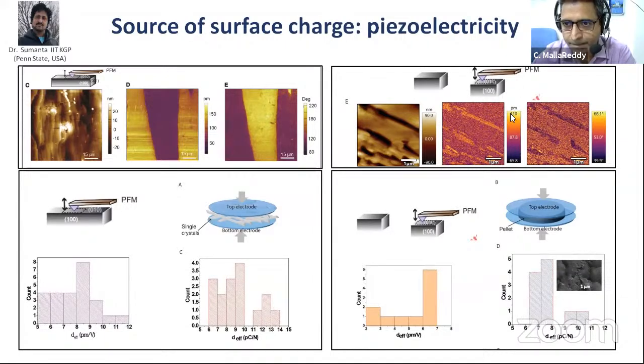So that is why the crystals are not as piezoelectric. The response is not as good as in the pristine crystals. So this tells that when you deform these crystals, there is a slight possibility of plastic deformation. So that is why there are some defects, and there is some fatigue in these crystals.